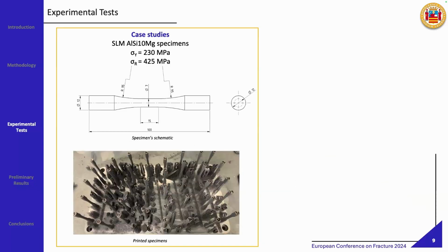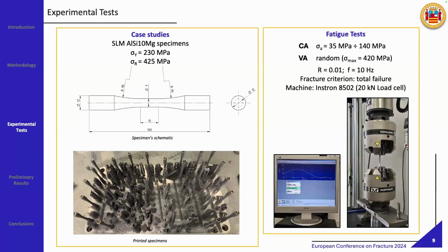So now moving on to the case studies. As I anticipated, they were specimens obtained by selective laser melting made in this aluminum alloy, so aluminum silicon magnesium alloy. Here you can see a schematic of the specimen and a picture of all the printed specimens, so the actual ones. We carried out tensile tests for obtaining the yield stress and the strength. And then we carried out fatigue tests.